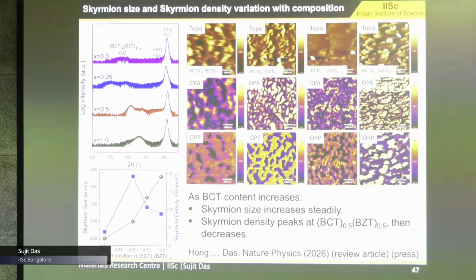So you can see these small bubble-like structures. We are claiming these as skyrmions, still not confirmed yet. We need to do a lot of TEM. And we checked the skyrmion size, which is increasing with the composition. Now, if we look at the skyrmion density, we found it is almost 20 gigabit per inch square for the 50-50% case. I didn't go through the topological details, so this paper is coming out tomorrow online. You can go through and check more details about that.